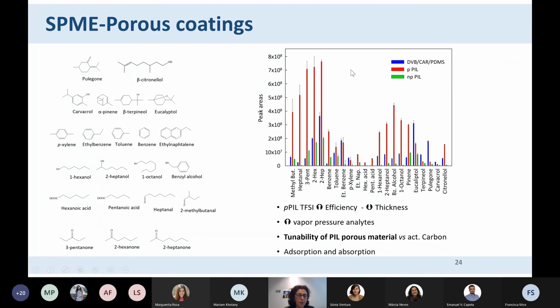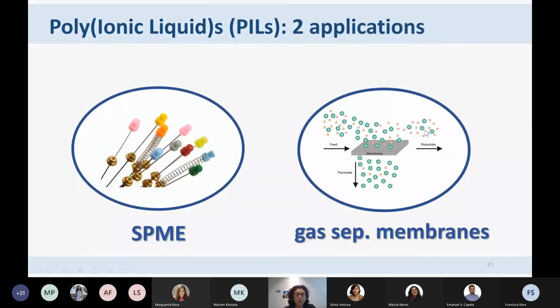So here we tested with a very wide range of compounds, and we can see between the porous and the non-porous that we gained a lot in using the porous. The pores open up more surface and speed up the sorption of our compounds. Of course, those that are more sorbed are those that have higher vapor pressure. And here we have adsorption versus absorption. And here we used one of the new commercial fibers by Supelco that also has carbon. And we can see that we have much higher peak areas than they do. So we are working in the right direction.